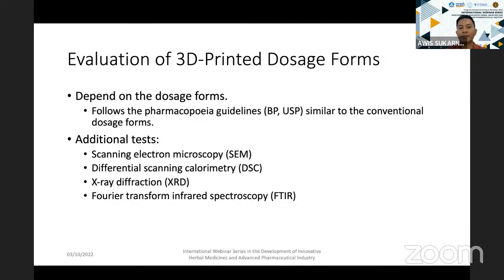Normally for this test, you need to do it with the physical mixture first, and then after that you need to test the sample that has already gone through the hot melt extrusion technique. So by doing this test, you can see if there is any interaction. If there is any interaction, then you need to find a new carrier or new polymer that doesn't interact with the active ingredient, the extract or the drug that you use.